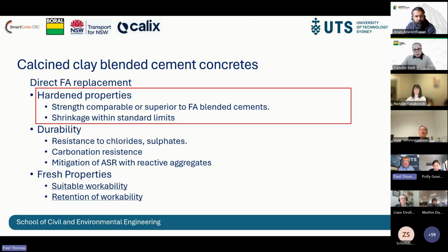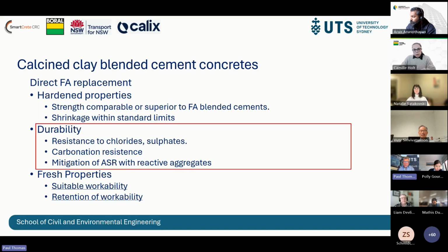Roughly speaking, the strength needs to be comparable or better than fly ash blended cements, along with a whole bunch of other hardened properties - shrinkage, creep, modulus, tensile strength, and so on. The durability also needs to be comparable, taking fly ash as the reference. Again, it needs to be comparable.